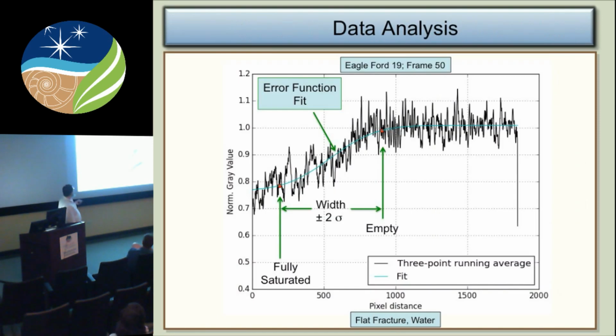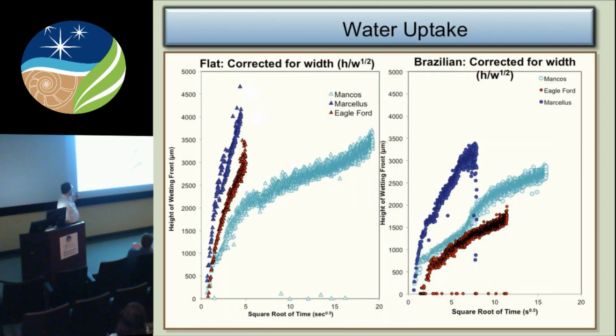than you will in the Marcellus, which suggests that the Marcellus actually would probably make a much better cap rock for a CO2 sequestration environment than would the Mancos. Much more reaction, much more permeability in what appears to be a fairly solid shale.